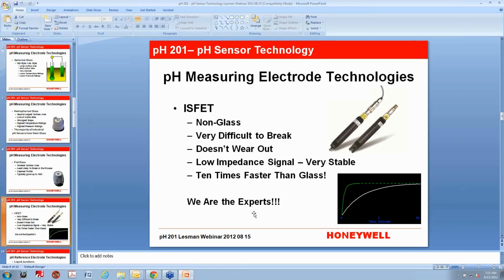And the really slick thing is it's about 10 times faster than glass, and that's what this little diagram is in the bottom right-hand side. That green line is a FET sensor. The white line is a good quality glass pH sensing electrode, and they were both put in a buffer at the same time, and you can see how quickly the green line gets up to the actual buffer value. It takes about a second for the FET to get to its value when it's brand new. For a brand new pH sensor with a glass measuring electrode, it takes about 10 seconds, which is not slow. That's pretty much what everybody sees, but a 1 second response time is pretty astounding.